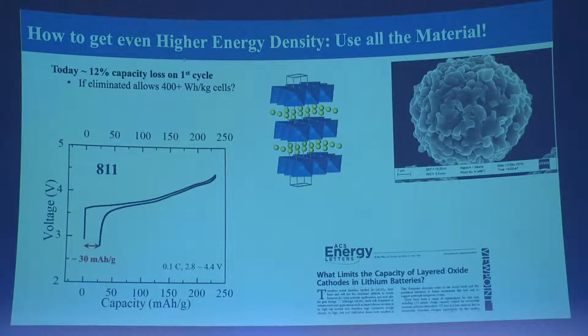But the thing we have been looking at, we're diffusing these lithium ions between these sheets. What we find is we can take the lithium out. When we try to put it back in, we never get the last 10% in at a reasonable rate. So on the very first cycle, you're losing somewhere between 10 and 15% of your capacity. That capacity is at about 3.5 volts, where these cells are very, very stable. So we have to use that capacity, rather than pushing them up to, say, 4.5, 4.6 volts, where the lattice changes much more. So we've been looking at what's the cause of this? Can we solve it? Can we recover this and keep it in use?